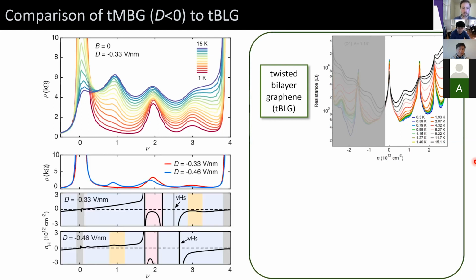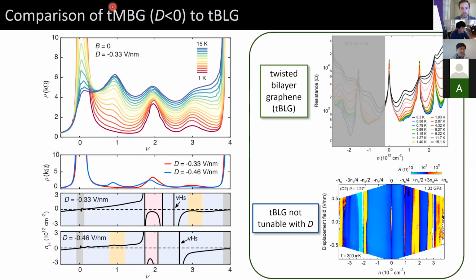And the thing that's different about twisted bilayer graphene and twisted monolayer-bilayer is that in this system, we have the ability to further tune these with electric field. So whereas these states are not tunable with electric field in twisted bilayer, we can turn them on and off at different displacement fields in twisted monolayer-bilayer graphene.